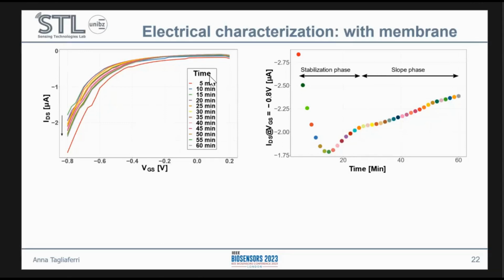If you remember, before we had a very rapidly decreasing current. Right now we obtained the opposite effect. If we plot the slope phase alone, we can see that the R squared is really, really high, higher than 0.99, and the current slowly but surely increases.